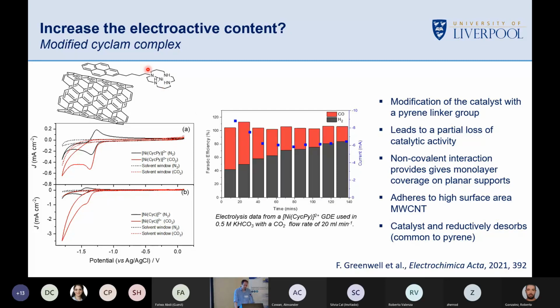This is actually just a near neutral one, and it works okay-ish. The big problem is that as you operate this thing, you have to push it to much more negative potentials to get a decent turnover frequency, and the pyrene actually desorbs. It doesn't help that much because we think you're just reductively desorbing the pyrene. So yes, we can increase the electroactive content. I think we can do it in much smarter ways than this, though, with these systems.